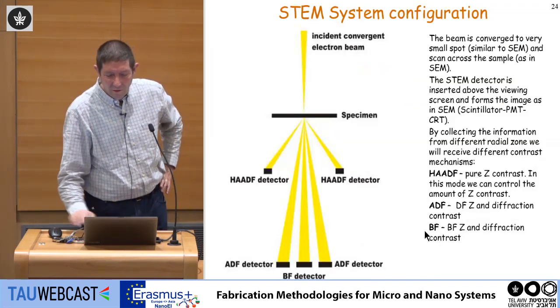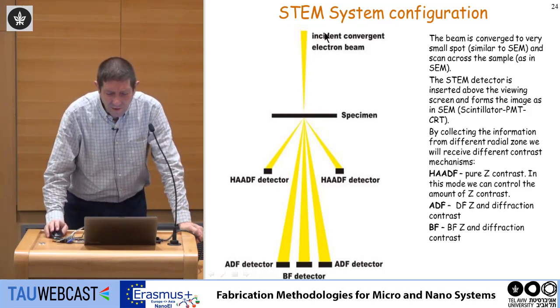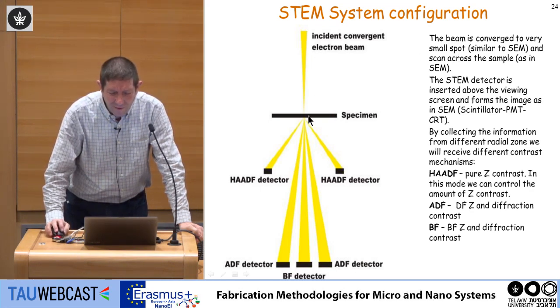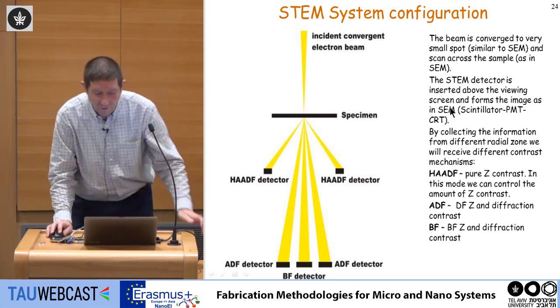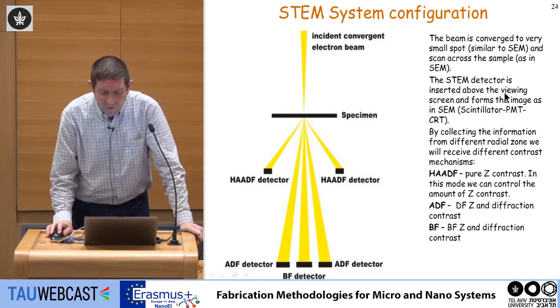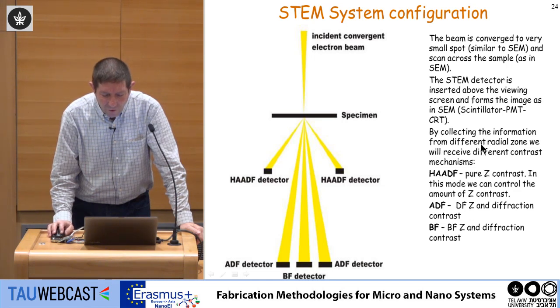There's another mode of operating the system. It's called STEM. The beam is converged to a very small spot, similar to SEM, and scans across the wafer. And here, we practically can put a detector here, or a detector here. Basically, the STEM detector is inserted above the viewing screen and forms the image in SEM. By collecting the information from the different radial zones, we'll receive a different contrast.